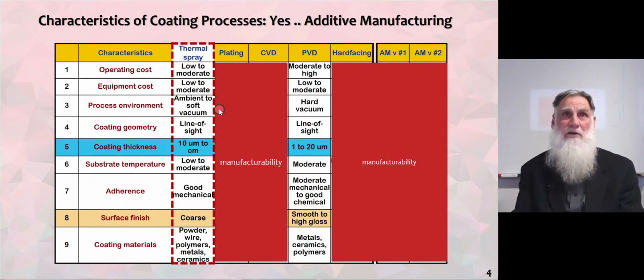First of all, we should look at and compare coating processes. And I've just outlined several in this sheet. I'm talking about thermal spray and physical vapor deposition. And these have a variety of characteristics, 1 to 9 and many others, ranging from operating costs to the materials that you can use. I've just highlighted 2 of these, one in the blue box and one in the orange type box. So coating thicknesses, for example, for thermal spray range from 10 micrometers to centimeters, while PVD is typically in the order of 1 to 20 micrometers.